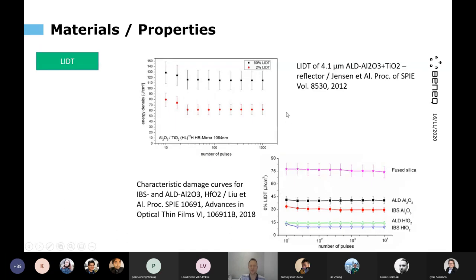An extreme example of the absorption is the laser applications, where you have very high power focused on a very small surface area. Even the slightest absorption can cause quite a lot of heating in the small area of the coated lens or whatever the object is. This heating can be so severe that it will cause very large local temperature differences, which may cause the lens to crack or even, in extreme cases, explode. So it's very important to have materials with very low absorption.